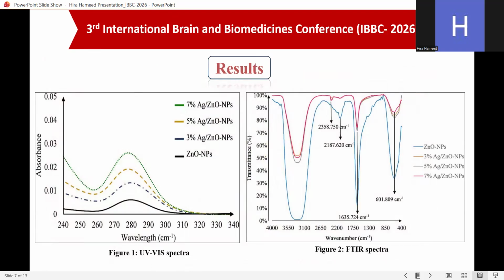Here are the results of this research. Figure 1 shows the UV-visible spectra. We can see different peaks of zinc oxide nanoparticles, then silver doped at 3%, then silver doped at 5%, and then 7%. On the right side, figure 2 shows FTIR spectra, and we can see its different peak values in per centimeter.